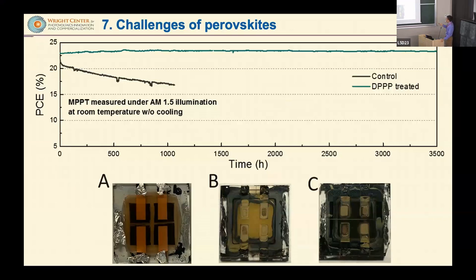So this is of course not acceptable, because for application this cannot happen. After incorporating these DPPP molecules, you see the device performance of the small cells, the stability, is improved so dramatically. After 3,500 hours, there's almost no degradation.